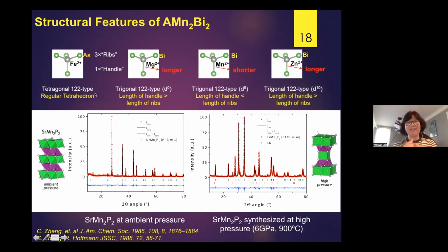They studied the chemical bonding in the trigonal 1-2-2 phase. They said the phase is very interesting because it only exists for d0, like magnesium 2+, d5, like manganese 2+, or d10, like zinc 2+, systems. If we look at the tetragonal system, the structure is like an umbrella, and the handle does not have the same distance as in the trigonal structures.